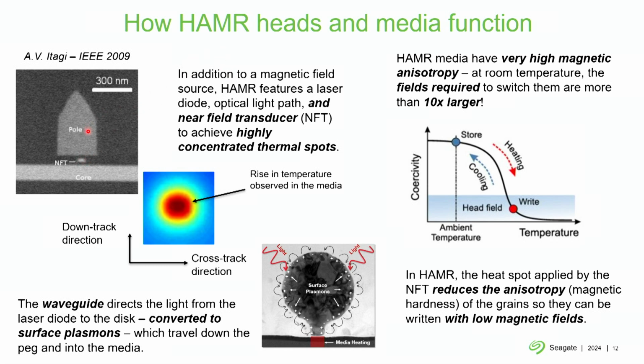So we still have the magnetic writer, but now we have a laser. And we need a waveguide to bring the light from the laser down to where the disk is. And we need to convert far field light to near field light. So we implemented a near field transducer, which is a plasmonic material that converts that incident light to surface plasmons, which travel toward the disk, the air-bearing surface. And they are concentrated at this peg, which is placed right at the air-bearing surface.